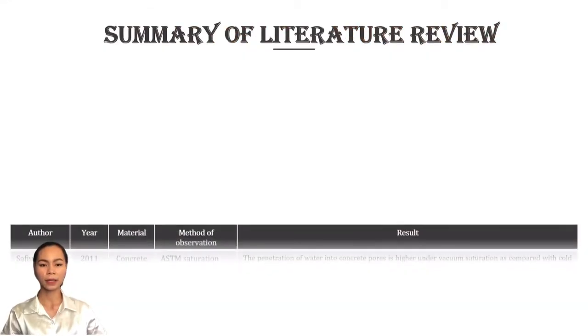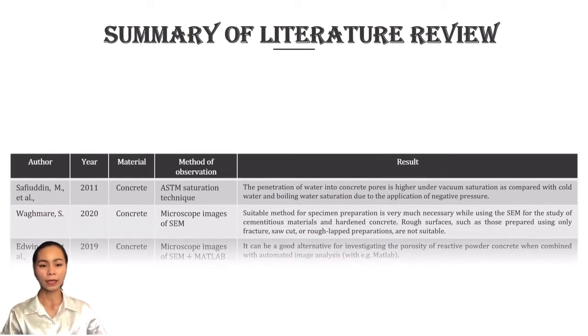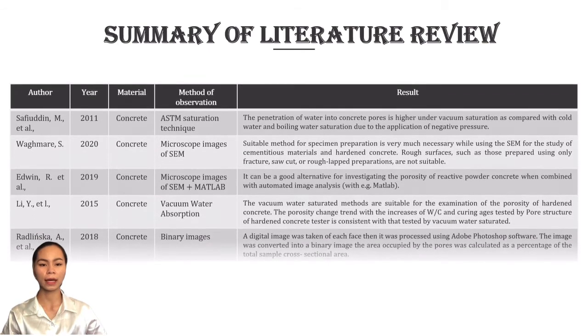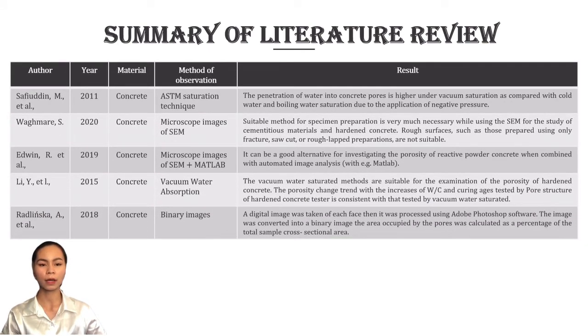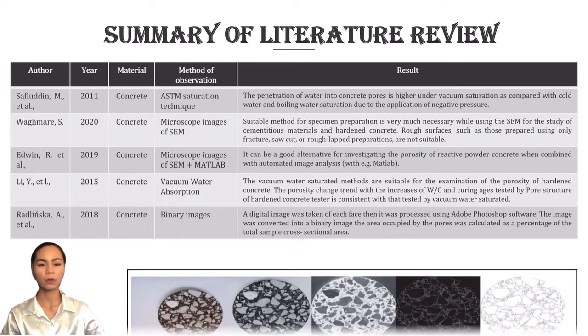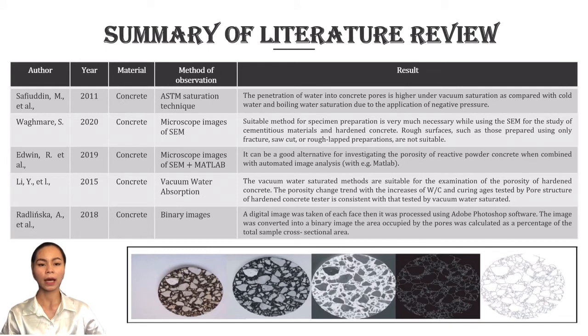Here is the summary list for the literature review in this project. Firstly, Safiuddin's research group used the ASTM saturation method to quantify the porosity of concrete, where they concluded and recommended the vacuum saturation technique to be used to quantify the porosity. Next, Waghmare used SEM to quantify the porosity of concrete. They stated that a suitable method in preparation of the SEM specimen is important because a rough surface on the specimen will cause significant error in data. Next, Edwin used microscope images of SEM with MATLAB, and their research was to quantify the porosity of reactive powder and concluded that it is a good alternative to investigate the porosity with automated image analysis,